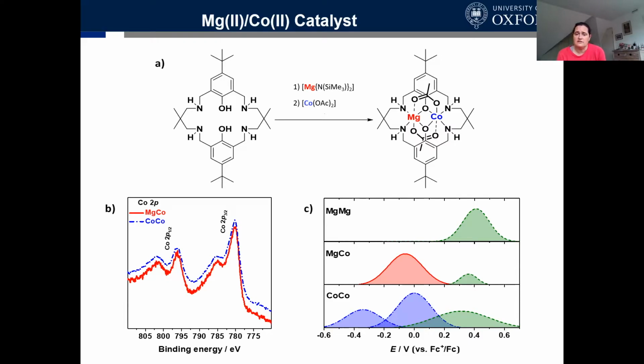The other thing we did was look at cyclic voltammograms of all of our compounds: magnesium, cobalt, and magnesium cobalt. We plotted the cyclic voltammetry data in a slightly unusual way, because we plotted, if you like, distributions for that electrode potential. But what you can see is that the ligand has an oxidation at about 0.4 volts versus ferrocene. The cobalt compound shows two oxidations, as you would expect, because there are two cobalts there and both of them can be oxidized to cobalt(III). Whereas our mixed metal species shows just the one, and it's at a different redox potential. That is providing us with further good evidence that we don't have significant contamination from any homodinuclear species.